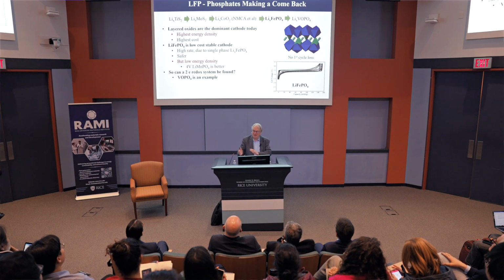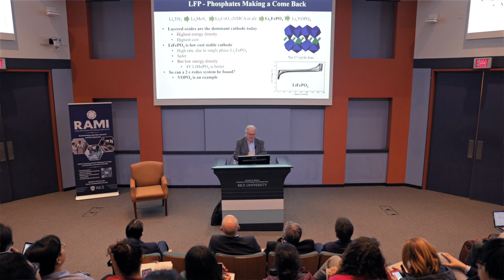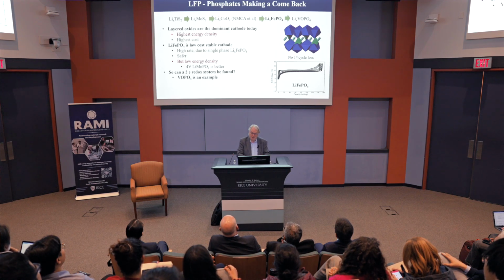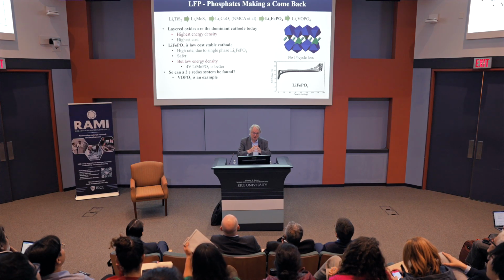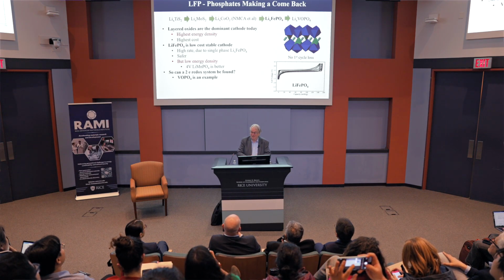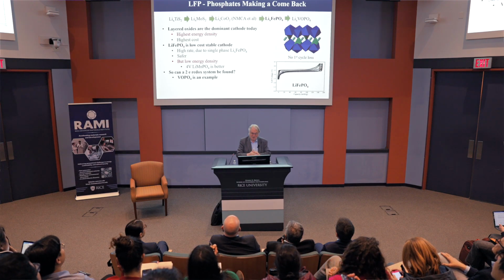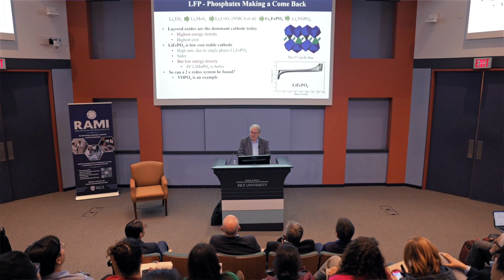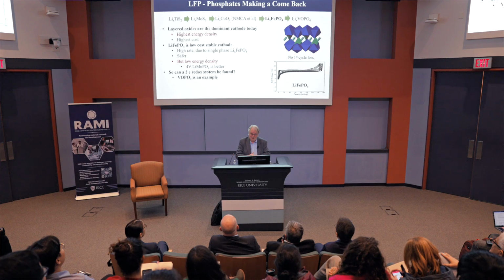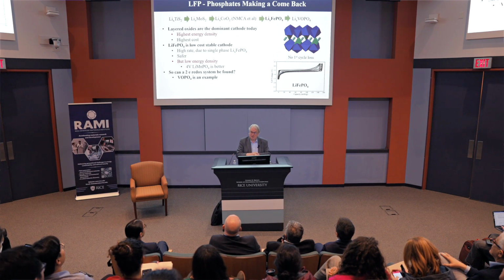So moving on from layered oxides, where a lot of the interest is, we started with titanium disulfide. The folks in British Columbia went to molybdenum disulfide because molybdenum disulfide is a naturally occurring mineral there. Then John Goodenough went to cobalt oxide, then lithium iron phosphate, and then the lithium vanadium. The oxides are still dominant because they have the highest energy density. Lithium iron phosphate is much lower cost because it doesn't have any cobalt in it, doesn't have any nickel in it, but it's a much lower energy density.